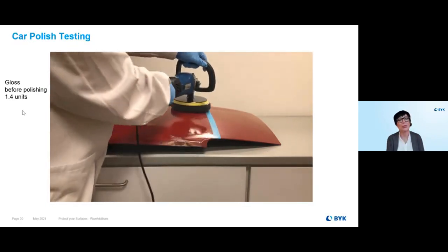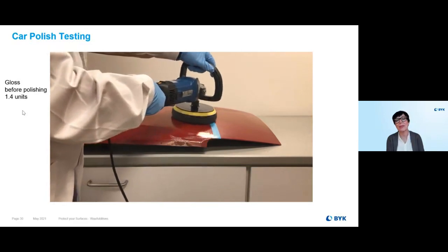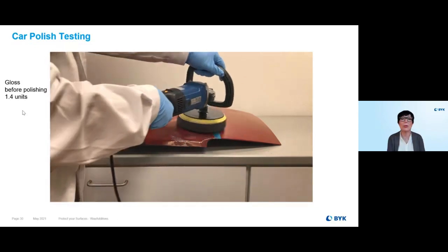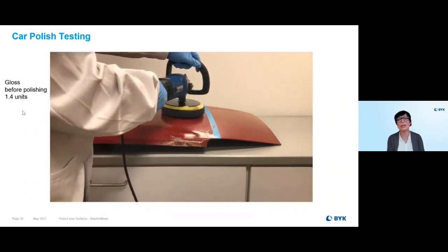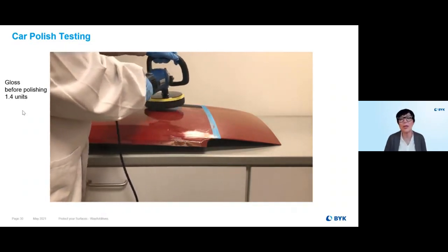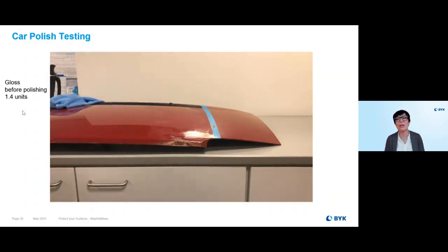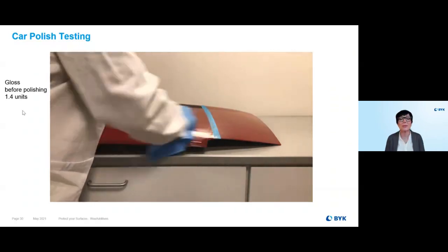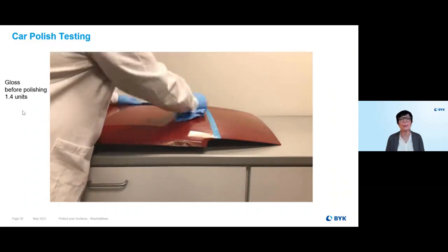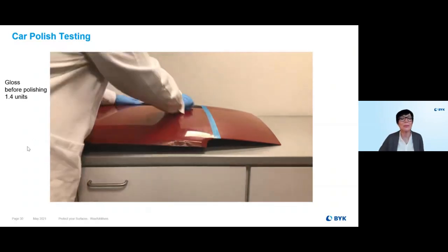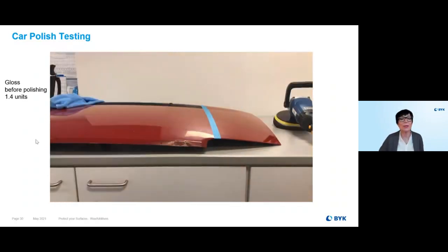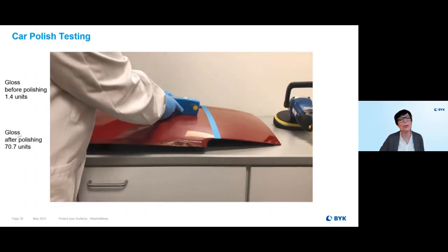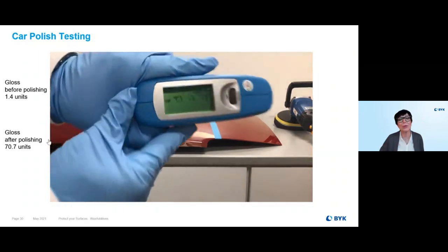In such a formulation you will find next to a wax the silicone emulsion which we talked about on Tuesday, the 9890, even Optigel WX for anti-settling of the abrasives. And last but not least, it results in a pretty nice gloss, which has a gloss unit of 71 after polishing.